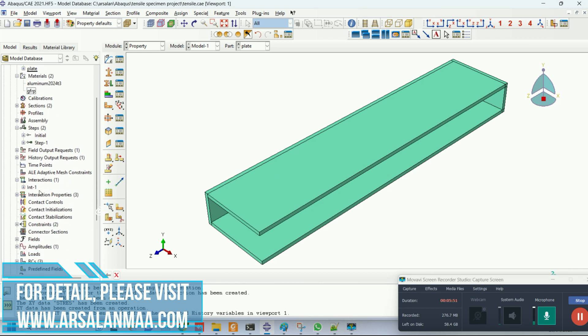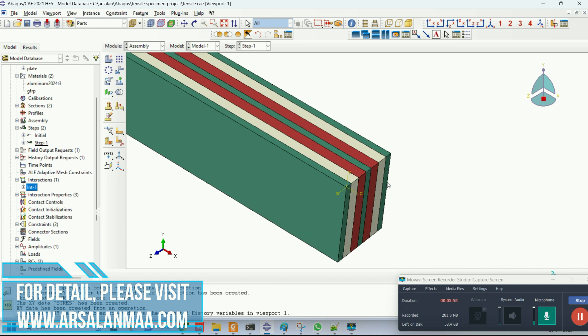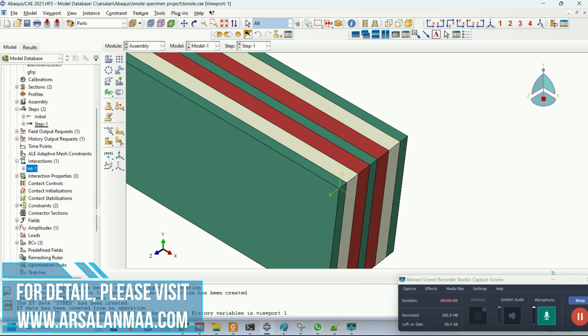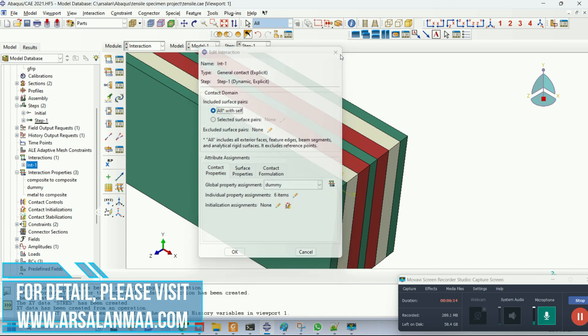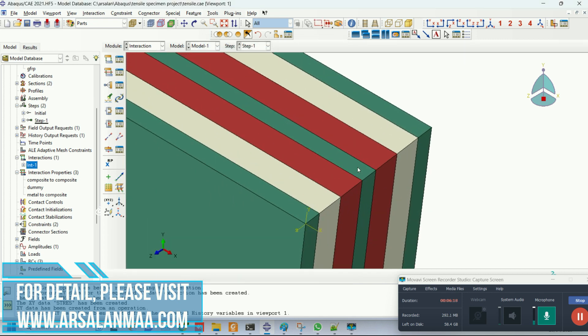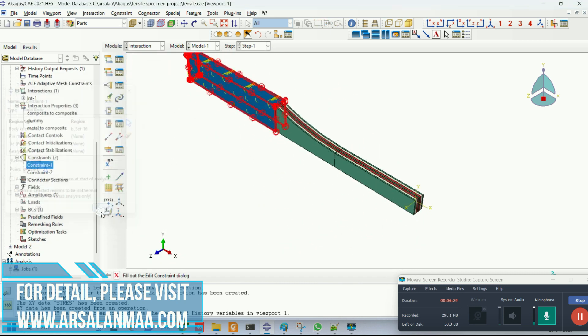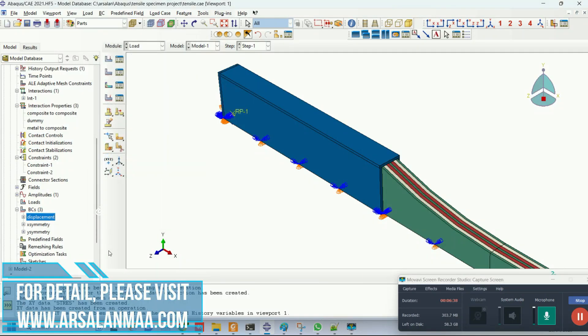Moving to the step definition and interaction module — this is the assembling sequence. The green portion is aluminum, the white portion is GFRP with 0° orientation, and the red portion is GFRP with 90° orientation. This is the composite sequence. I have used the cohesive zone approach between layers to model delamination. The holder is modeled as a rigid material used to pull the specimen. The load is applied as a displacement boundary condition at the center point, and the results are evaluated.